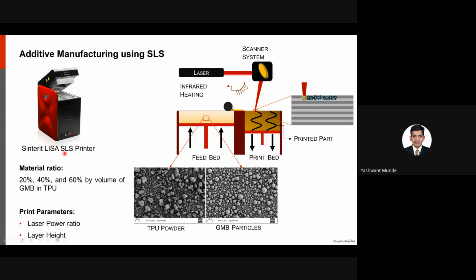So we used the selective laser sintering, SLS, printer, and we incorporated GMBs in ratios of 20, 40, and 60 by volume. And we looked at 2 print parameters primarily, laser power ratio and layer height. So in an SLS, we start with this powder mixture in the feed bed, which is rolled onto the print bed, and a laser is shined onto this powder mix, which locally sinters the particles together. Then the print bed is moved down, and the next layer of material is raked onto the bed, shining the laser again, creating the next layer, and so forth, building the full 3D structure.